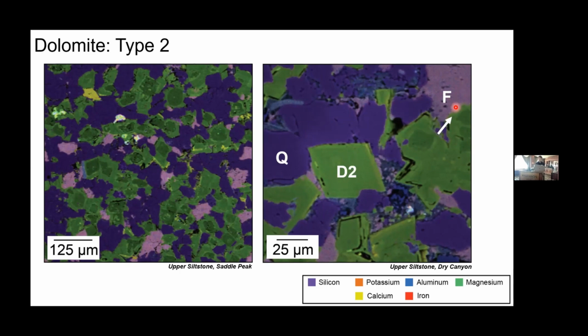Something else that's interesting about this phase is that both the type 2 dolomites and the type 1 rims are commonly found replacing detrital feldspar. So you can see this arrow here where this crystal is growing into this detrital feldspar grain up in the top right view of this EDS map.